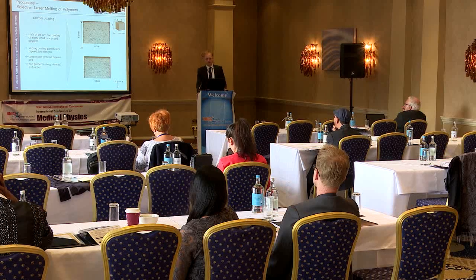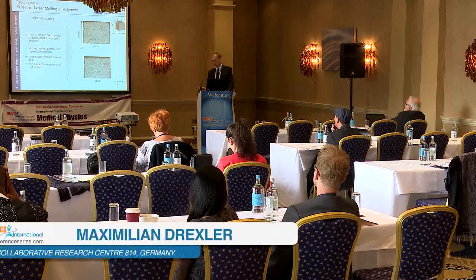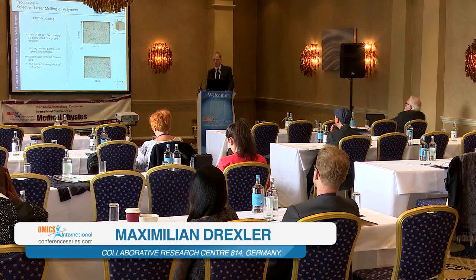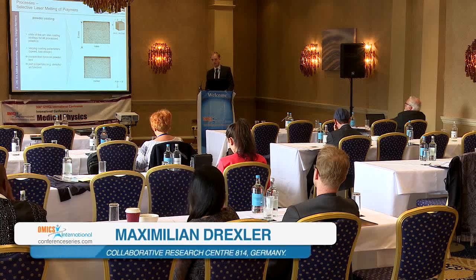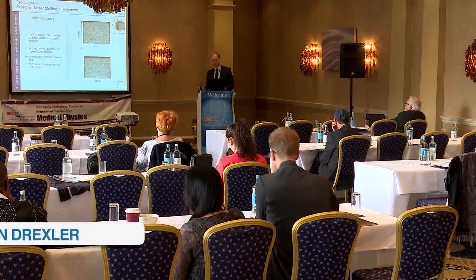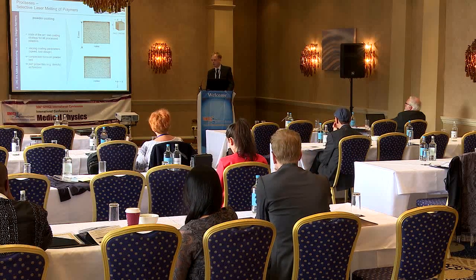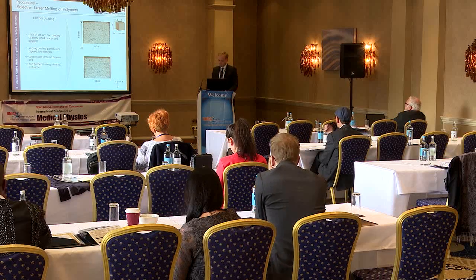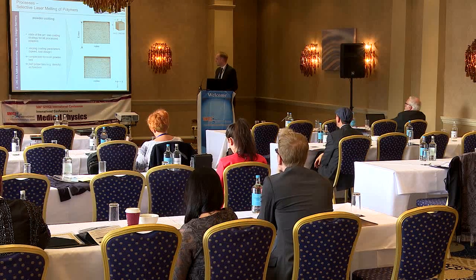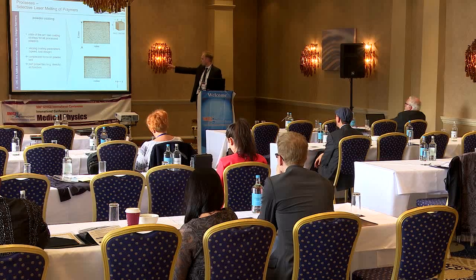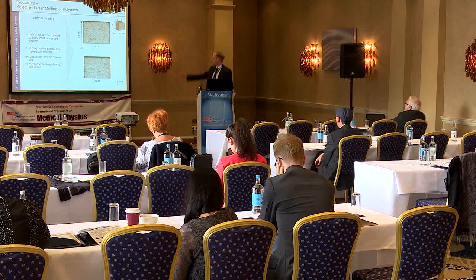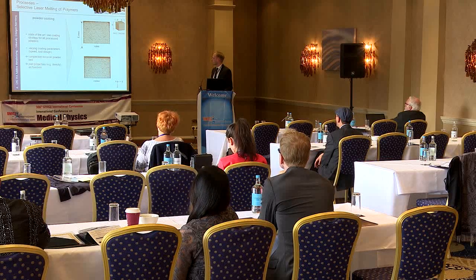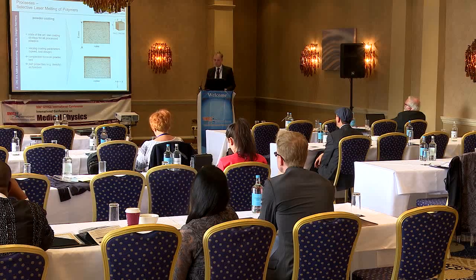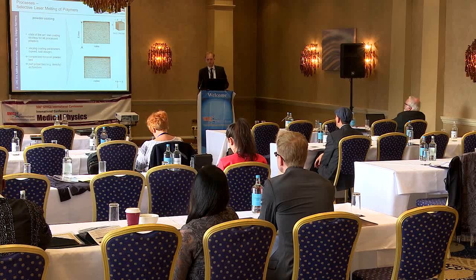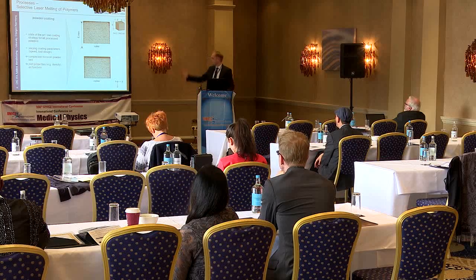And we tried to investigate what happens if we meet the requirements of our polymers. So we know, okay, this polymer has a little bit larger particles than the other. How can we meet these requirements? For example, by adapting coating parameters. And as you can see here, by adapting coating parameters in the right way, you can get from a part with a very high porosity, where you can see even the single layers, to a part with a well-distributed porosity. The layers are better connected, and so you have a better property distribution over the whole specimen. The specimen was a cube, and these are some CT scans of this cube.